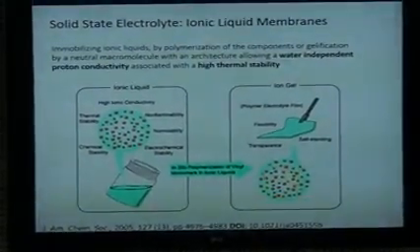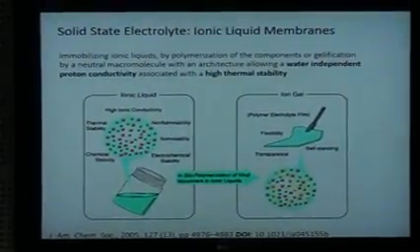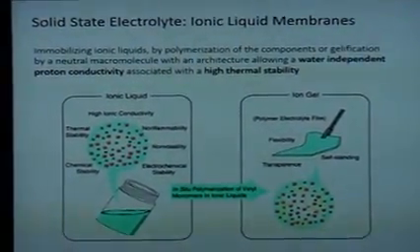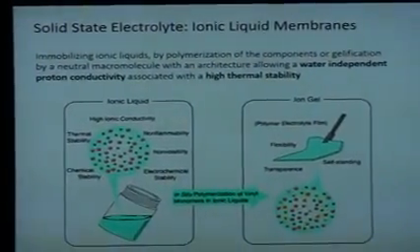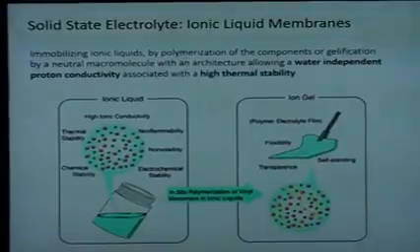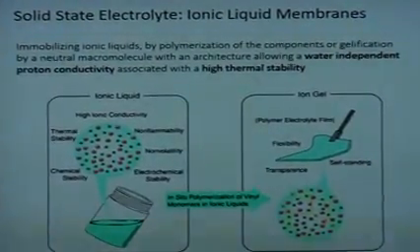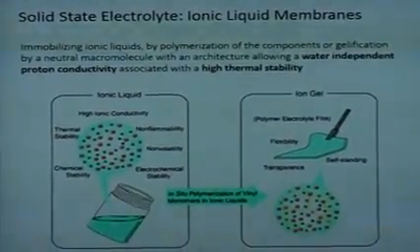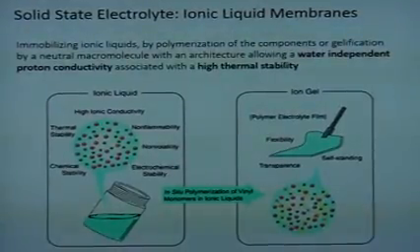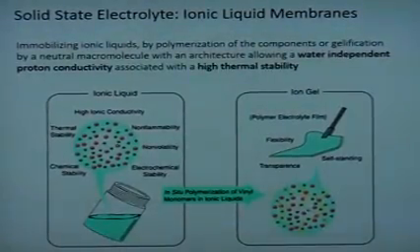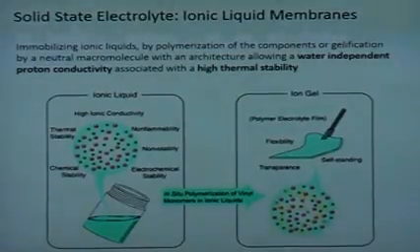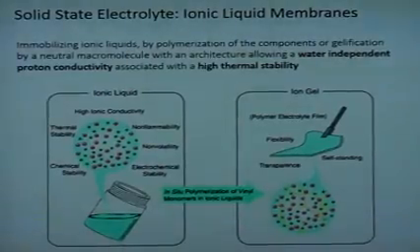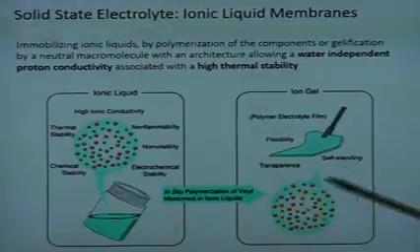One can make solid state electrolytes using these ionic liquids. One can cross-link them inside the polymer in situ, and that way one can have ionic liquids immobilized in the polymer matrix. And usual polymers which are chosen are like PMMA, PEO, polyethylene oxide. These are kind of polymers which can dissolve the ionic liquid, and it also encapsulates them from aerial oxidation. So once you have ionic liquid dispersed in these kind of polymers, you can use them outside the glove box. So that's the advantage. So making these kind of self-standing films